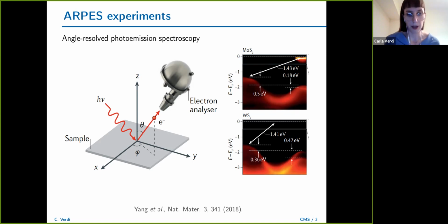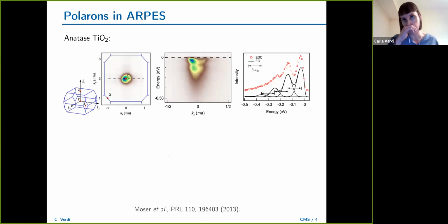Now remember, phonons have energies of the order of 50 meV, or up to 100 meV or so in this sort of solid state materials. So you really need a very high energy resolution in order to resolve structures that are related to the coupling with phonons. In fact, there was a very nice experiment that was published back in 2013 by the group of Marco Grioni at EPFL. And they did ARPES on anatase TiO2.